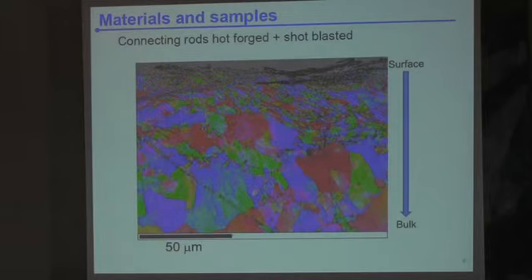So, what does it give? In terms of microstructure, this shot blasting process has a dramatic influence on the grain size, and this is shown here. This is an EBSD map showing the grain size evolution between the surface and the bulk. I'm showing here roughly 150 micron. This is the scale bar here, and you see that at the surface, by the repeated contacts and the component rotating in this barrel, you get a very small grain size at the surface. I mean, they're of the order of 1 micron.